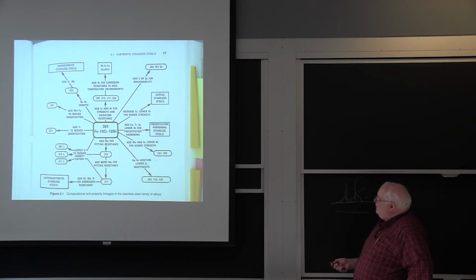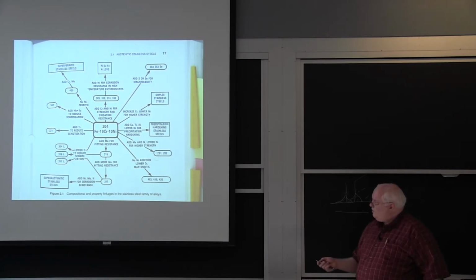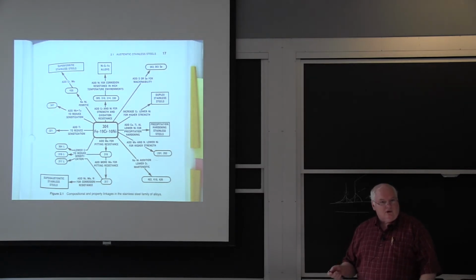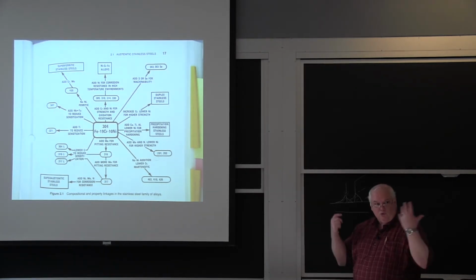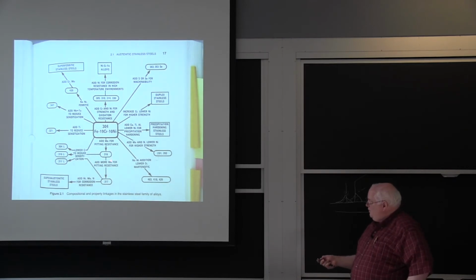You can add some molybdenum. 2% molybdenum makes 316. 4% makes 317. 317 is often used in the body where you have high chloride concentrations. It's not very common. 316 is fairly common. This is what they were supposed to use in my hot dog cooker. Okay, and they didn't. They used 304 and it just corroded. So this is for pitting resistance mostly in chlorides. If you go to a low carbon variety, we're going to talk about that in a little bit, this improves the weldability and the corrosion resistance.